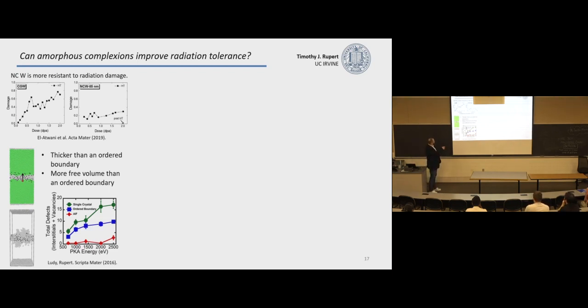This is an example here of people using energetic ions to bombard a material, and look how much damage builds up. And by having a nanocrystalline material with lots of interfaces, you can get less damage. So these can be sinks for that damage. We've studied this in the context of these amorphous grain boundaries and seen that we get much less damage compared to ordered materials or single crystals.